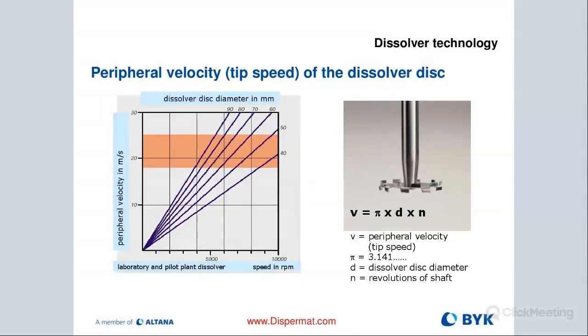And here is the important formula to calculate our tip speed. We have pi multiplied by the diameter of our milling disc, multiplied by the RPM or the shaft speed. If we want meters per second, as displayed on our machines, we divide everything by 60. But keep in mind that the diameter of our blade needs to be expressed in metric, in meters. So if we have a 50 millimeter blade, we use 0.05, multiply that with pi and the RPM, and then divide that by 60. That will give us our actual tip speed in meters per second,